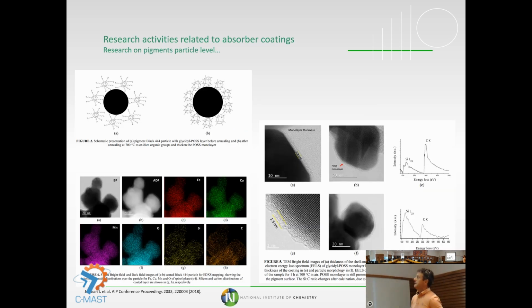So as I said, this is mainly related to the elemental level, nano level. As I told you already before, those things could change at high temperature with diffusion. We observe quite often that if there is diffusion from below inside the pigment structure, the high absorption is lost. So in the next step, I'm presenting what we do on pigment level. As you could see here from transmission electron measurements, sometimes we try to modify the pigment particles just to protect the pigment against diffusion from other elements.